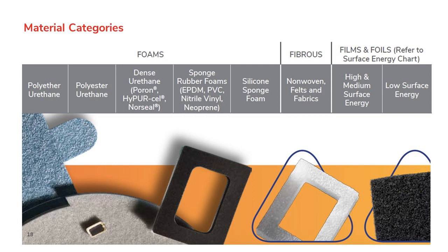And most of you know this, silicone can be very difficult to bond to, and there are sponge versions of this material that are used for gasketing applications. And we have really only one product we recommend for that if you're going to be laminating without a primer, and that's FT9302, which has a silicone adhesive on the one side that can bond to silicone sponge foam materials.